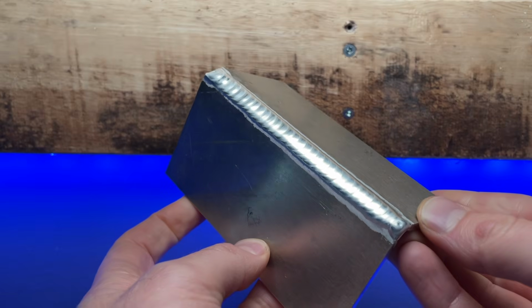We can see that the arc focus here is very good. Again, the standoff distance is in nice and close. The arc cone is focused and tight. We can see that the filler material is being added pretty much perfectly while allowing the heat to get down into the base material. Taking this one after the fact, looks pretty good.